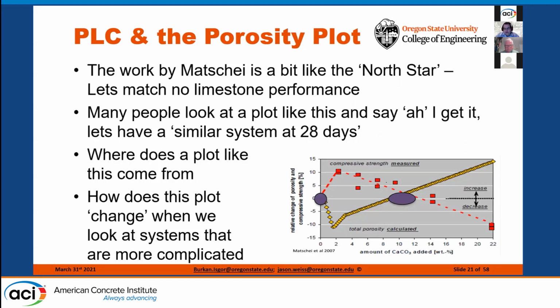Now, the reason I point that out is we want to use this plot from Duncan Herfort and Thomas Matschei, because this has really been a little bit like the North Star, as Doug mentioned earlier, that really starts to describe the concept behind using these PLC systems. So the basic idea is we're going to get a certain amount of porosity in the system. If we add a little bit of limestone to the system, we're going to see that porosity decrease because of additional hydration or reaction products that can form. However, over time, that porosity will start to go back up.